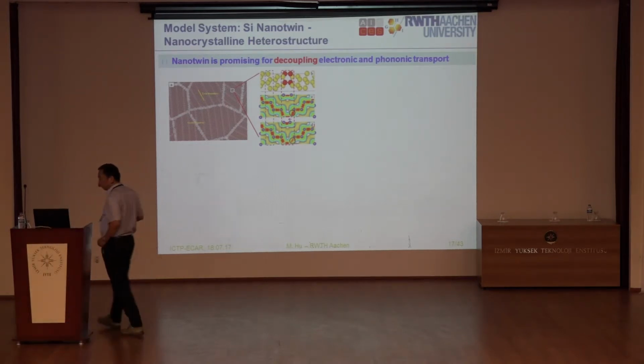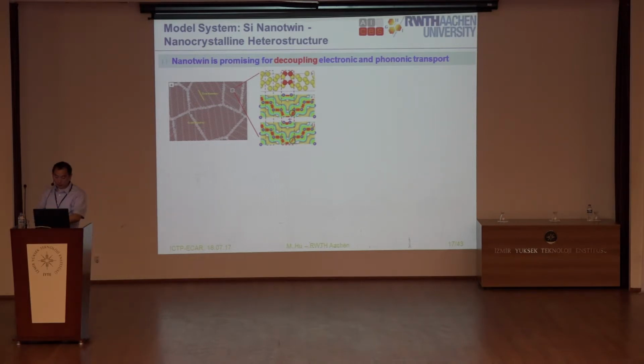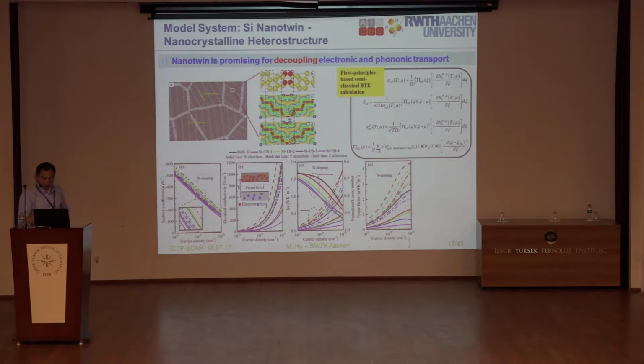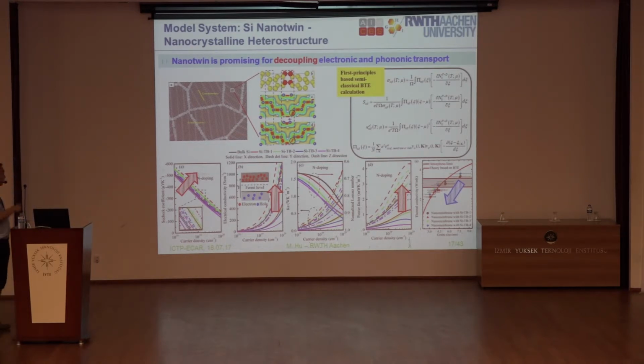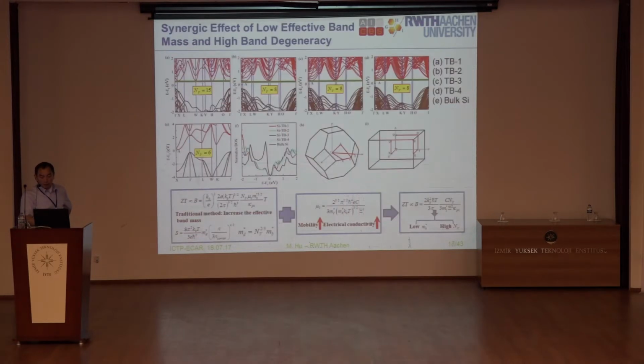And then with semiclassical BTE calculation coupled with first principles, you can find that the Seebeck coefficient and also the electronic conductivity for some nano-twin structures are enhanced. At the same time, you also find that the phonon transport goes down. That's easy to understand because you introduce some boundary, right? Because the nano-twin is also a kind of boundary to scatter phonons. So you can see that the electron part, the power factor, enhances, and the phononic transport decreases. And then actually you can decouple this.